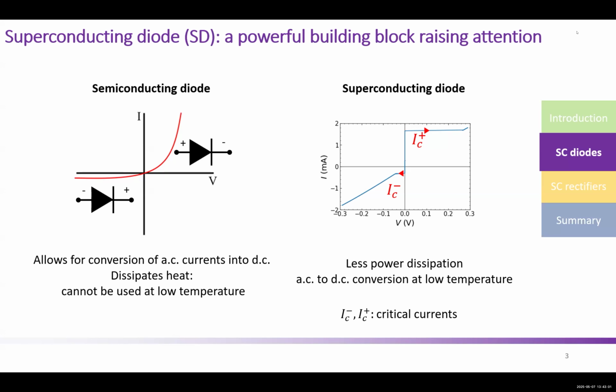But you know everything has a limit, and superconductors have a limit which is called critical current, and that is how much current they can carry without heat dissipation. Now, if we make that critical current direction dependent, meaning that when you apply a positive current, you need a lot of current to drive the system resistive, and when you apply a negative current, you need much less current. What is going to happen is that you also have this kind of non-reciprocal response, which is very asymmetric between positive and negative voltage. And now that may allow also for the AC to DC power conversion at low temperatures, but with a lot less power dissipation because in this whole regime, you're not dissipating heat.